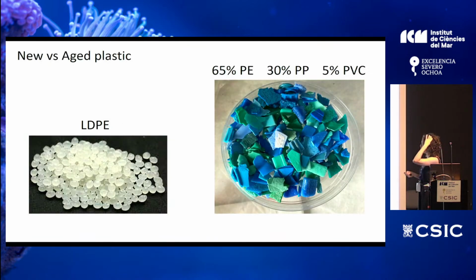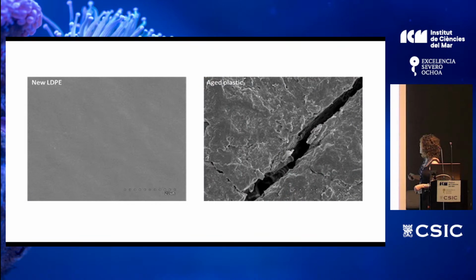So we used two types of plastic, LDPE. We used pellets that were new, and then we used aged plastic that we collected on the beach. The composition of this plastic was 65% polyethylene, 30% polypropylene, and 5% PVC. So with this, we generate the leachates in the way I showed you before. Here is just to show you in the electron microscope how the surface of each one looks. This is the new plastic, and the aged plastic presents a lot of scratches, so it's very different.